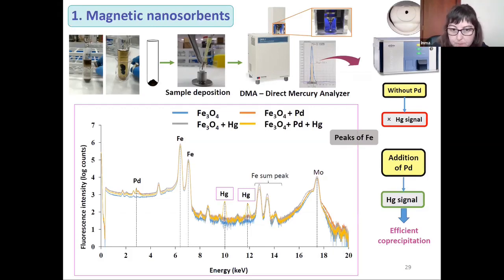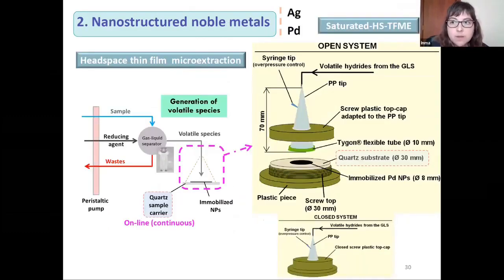palladium. Here we can see the peaks of iron, which are also higher, making difficult the analysis of elements at these energies, and also double energy. And then also we have the molybdenum peak corresponding to the X-ray tube. In other publications of our research group, we worked on the generation of volatile species. It means hydrides and mercury vapor.